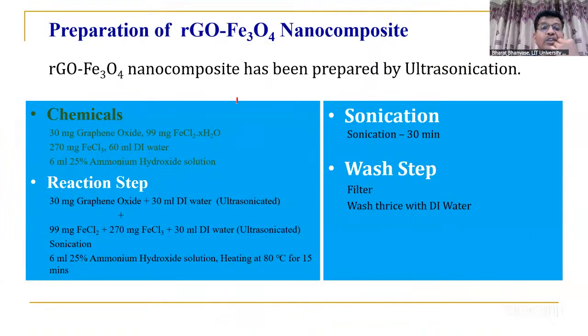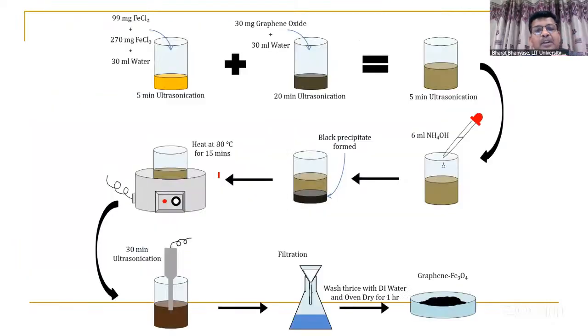So if you want to load Fe3O4 on this, we need FeCl2 and FeCl3 that can be added, and then by addition of ammonium hydroxide, the formation of Fe3O4 nanoparticles will be done on the surface. So for that, what we did is addition of FeCl2, FeCl3 and water, that forms one mixture.